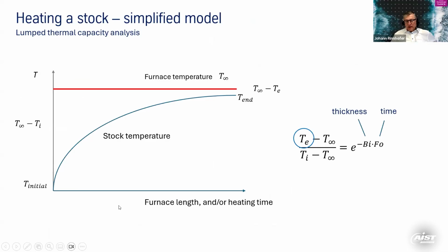So in the end, you can look at this in a simplified model. You say you have a furnace at the temperature T infinite, and you have a stock which is heating up like this. So you have an initial temperature, and you have an end temperature of the stock after the heating process. You have a temperature difference initially, T furnace minus the T initial of the stock, and you end up with a difference in the end, temperature of the furnace minus end temperature. And this is what we will see now, you will end up with this equation for a thin stock. So the temperature difference at the end divided by the temperature difference at the beginning is equal to e to the power of minus the thickness and the heating time. And that's very easy to calculate. We don't go into too much detail because it's a bit awkward probably, but this is how it works.